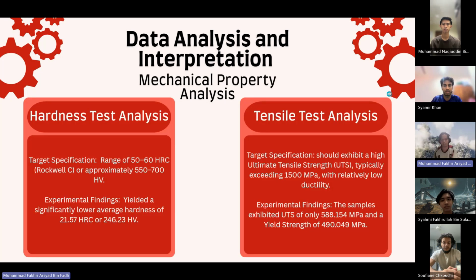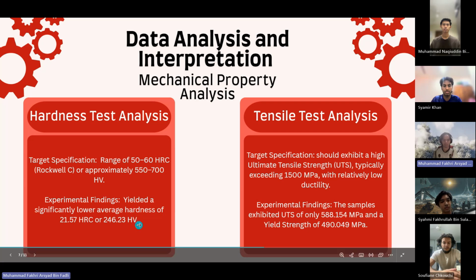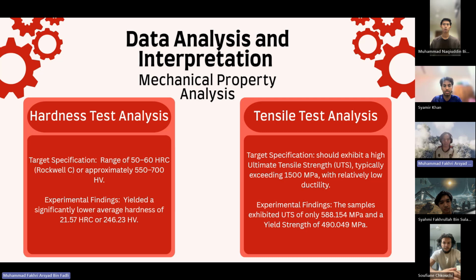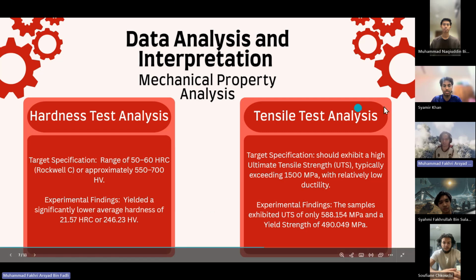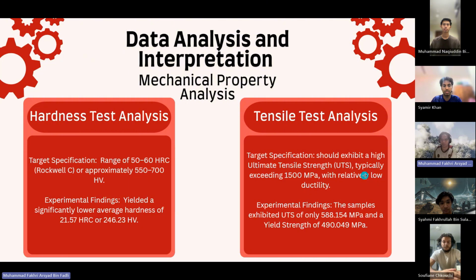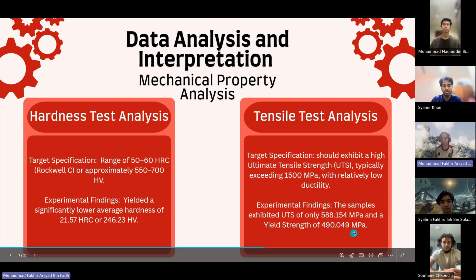From these findings, we did our tests, which are the hardness test and also the tensile test. The target specification for the hardness test is between 50 to 60 HRC, which is Rockwell, and also approximately 550 to 700 HV hardness. From our experiments in the lab using the carbon steel, it yields significantly lower average hardness, which is 21.57 HRC and 246.23 HV. And also, the tensile test analysis shows that it is a bit low from the target specification, which is 1,500 megapascal. But the samples we used only give us 588 megapascals and also 490 megapascals.